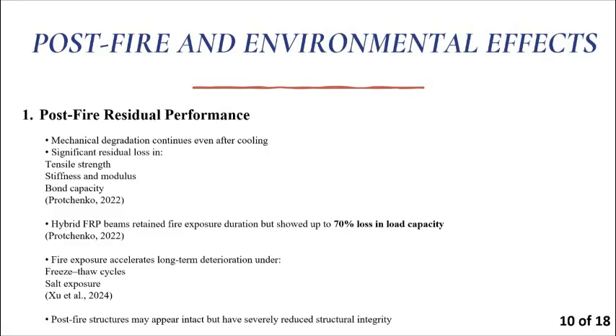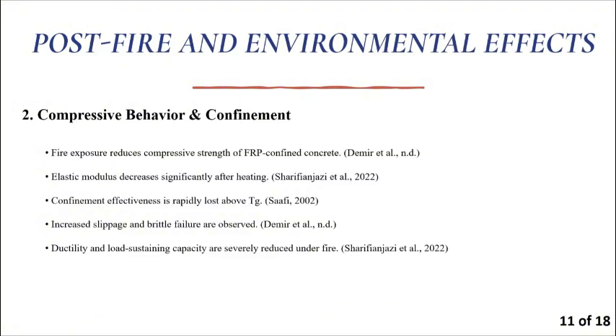Another important problem is the bond between FRP and concrete. After fire, this bond becomes weak, as we have just mentioned in the previous slide. So even though they did not collapse during the fire, it will not work. Sometimes the structure may look fine from the outside, but inside the reinforcement has already been seriously damaged. So even if the structure survives the fire, its residual strength and safety level may be greatly reduced.